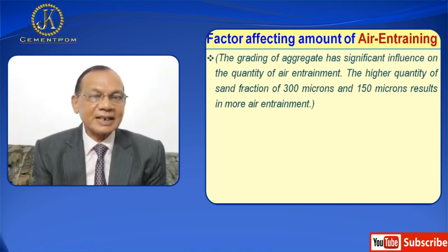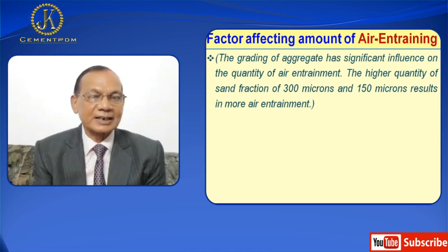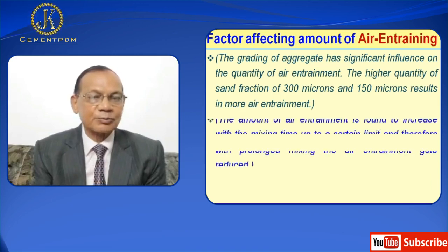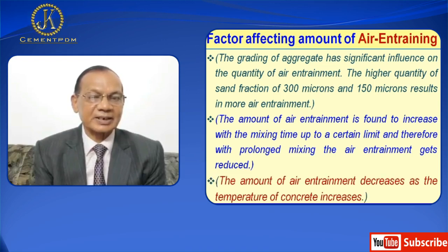The grading of aggregate has significant influence on the quantity of air entrainment. A higher quantity of sand fraction of 300 microns and 150 microns results in more air entrainment. The amount of air entrainment is found to increase with mixing time up to a certain limit, and with prolonged mixing the air entrainment gets reduced.